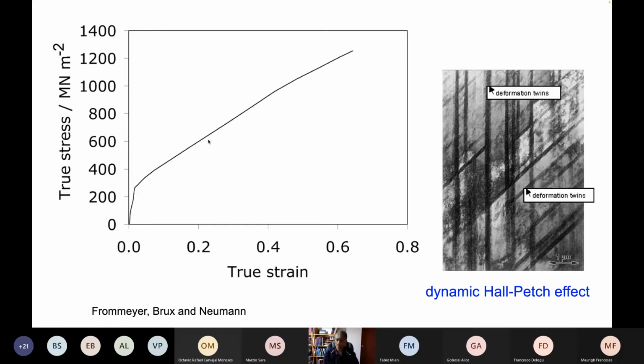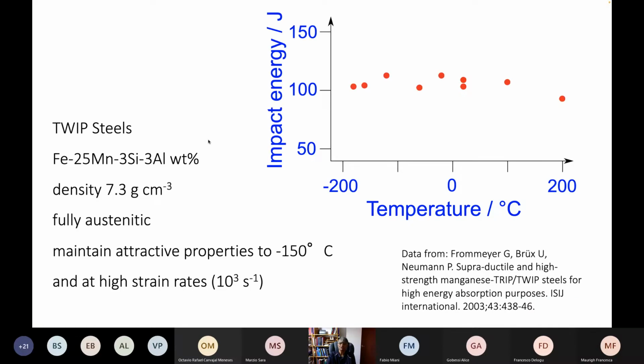So we are not transforming this austenite at all into martensite or anything like that. It's just mechanical twinning, refining the effective grain size as deformation proceeds. And the mechanical properties are quite remarkable, apart from the strength and elongation. If you look at the impact energy as a function of temperature, there's virtually no change. If you recall what I said about the ductile brittle transition temperature, the austenite does not have a ductile brittle transition temperature because the flow stress always remains below the cleavage strength.